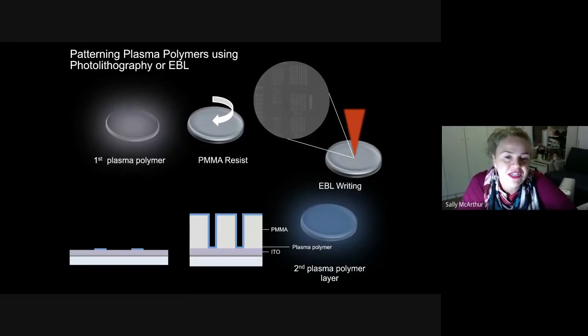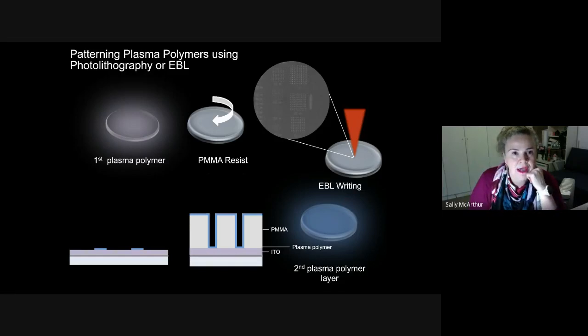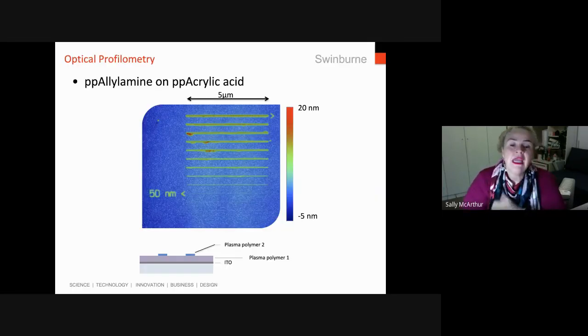Obviously, the process of actually removing that resist when you're at the nanoscale is the challenge here, because you've got quite a thick layer of resist and a relatively thin and soft layer of plasma polymer sitting on top of it. So part of the question is tearing of the actual plasma polymer, lifting it off, delaminating it from the surface at the same time. And that's pretty much what we saw. In this case, what we've done is we've deposited a polyallylamine coating, an amine coating, on top of an acrylic acid plasma polymer. We're using an ITO substrate because of the EBL requirements as well.